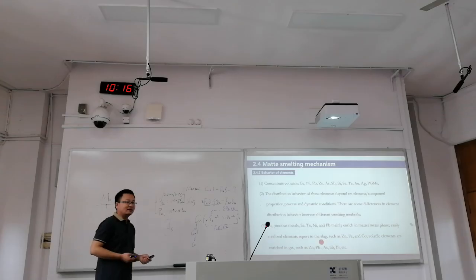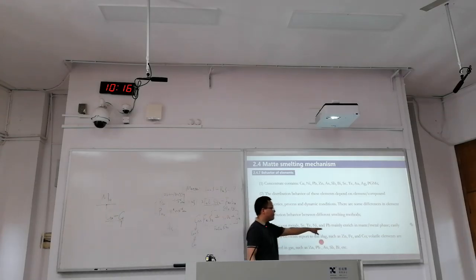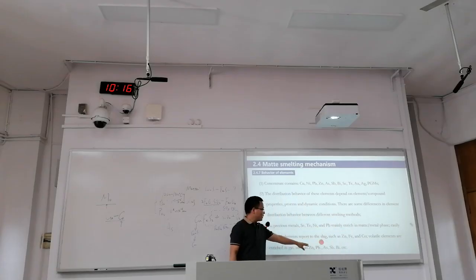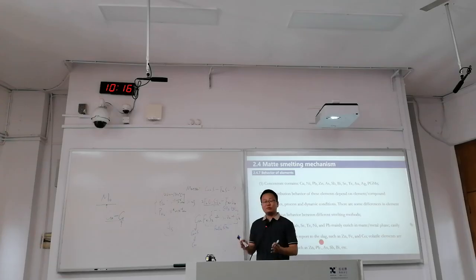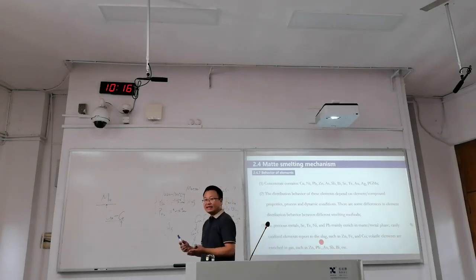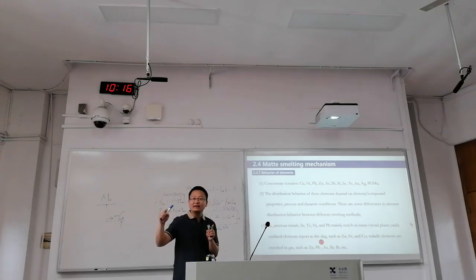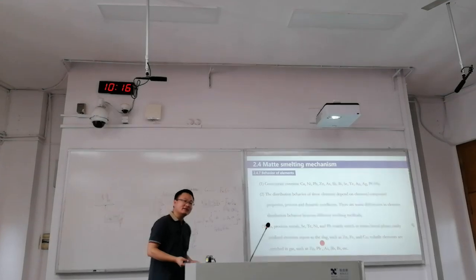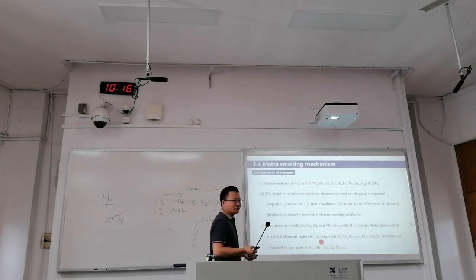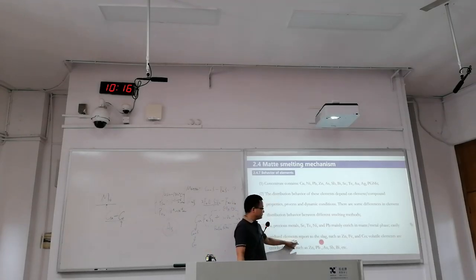I have been discussing with them, and I told them that when we have copper in the metal phase, we have cobalt in the slag phase. So if we are using pyrometallurgy, copper can be easily recovered, but the recovery of cobalt will be from the slag. So we are going to have a long flow sheet, and they agree with this, and we will try to make a flow sheet for the company in the following half year. Okay, so this is something we know.